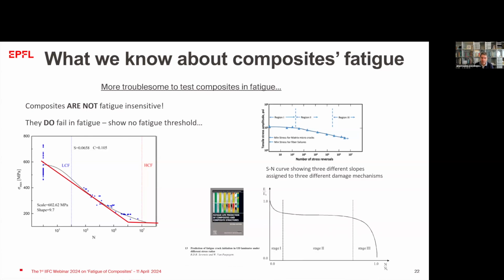We also know, and this is a very typical schematic diagram showing the stiffness degradation of composites, that the stiffness drops initially during this stage 1 of the fatigue life, and it is more or less stable for a long period. This might be probably 80% of the fatigue life, and then drops at the end. The level of drop, so here I'm going close to 0, but in some materials, especially when we have unidirectional materials tested on axis along the fibers, the drop might be 2%, 1%. And when we have off-axis materials, then the stiffness drop is much higher.